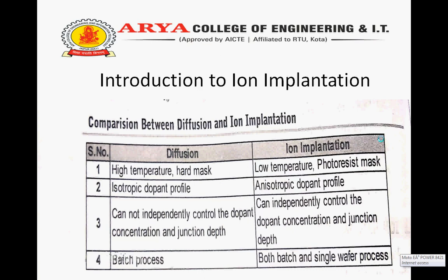If the energy of the beam is adequate, the ion can penetrate the target wafer, collide with the silicon lattice atoms and with the electrons surrounding them, and eventually come to rest within the wafer. This is called ion implantation. Alternatively, the beam energy may be sufficient to knock off or remove atoms from the target, and so can be used for selective removal of material. This is called ion milling.